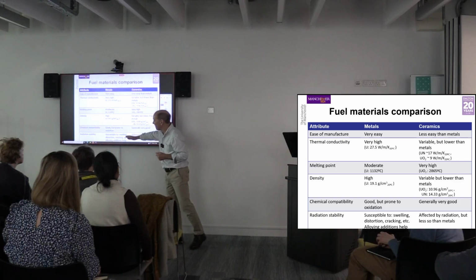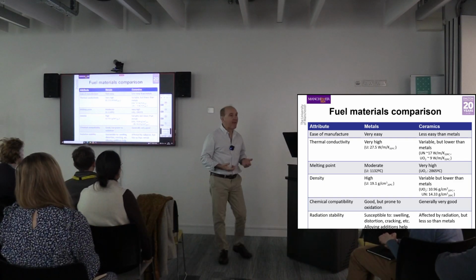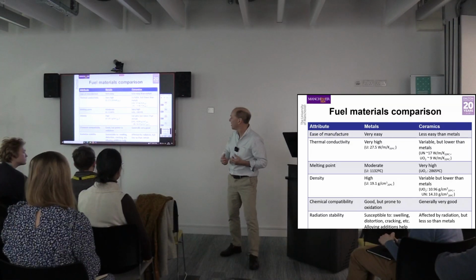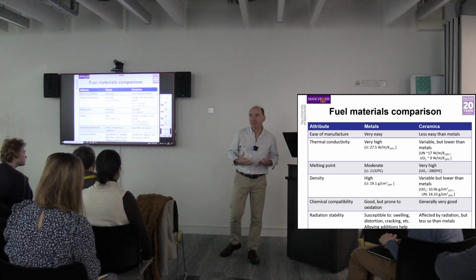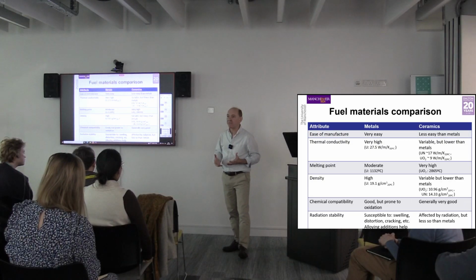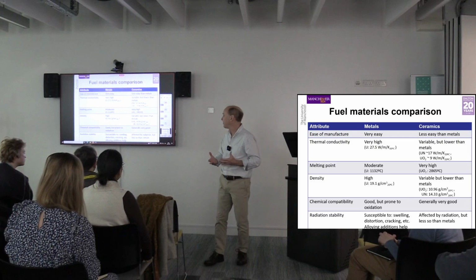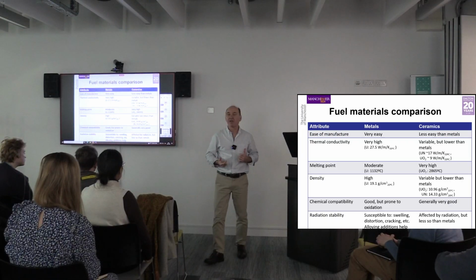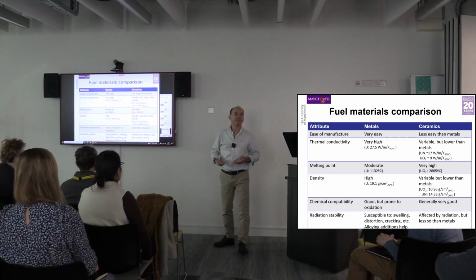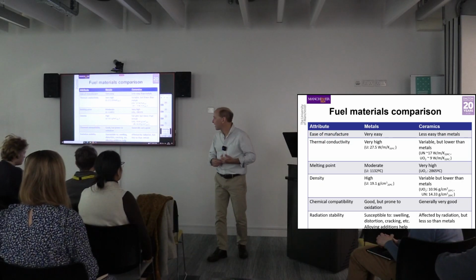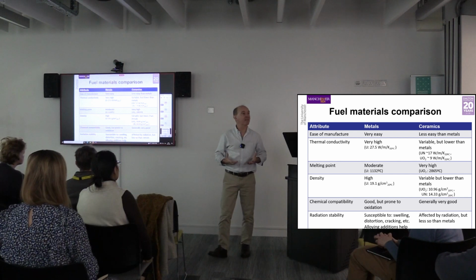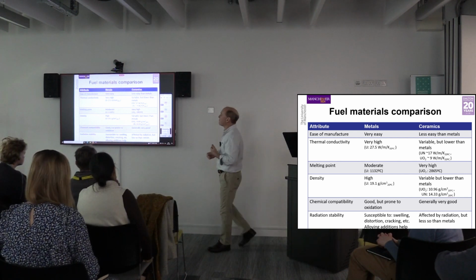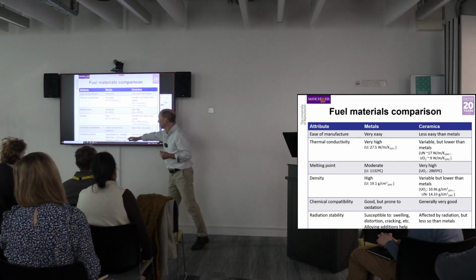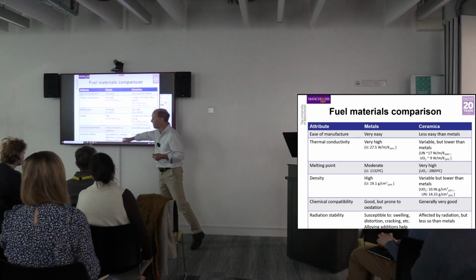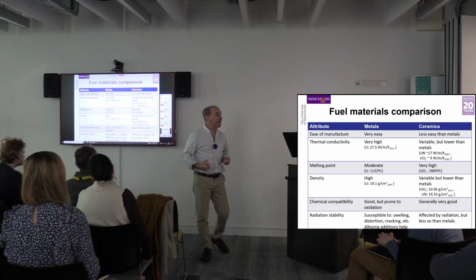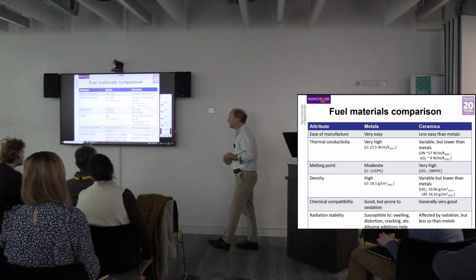And finally, radiation stability. So we're going to put these materials into the core of a reactor. What's going to happen to them? What's going to happen to their structures? Well, quite a lot, actually. Everything is affected by radiation. Absolutely everything. Nothing is immune, perfectly immune to irradiation, with the possible exception of some of the noble gases. So helium, for example, is almost unaffected by radiation, but pretty much everything else, and certainly everything with a solid structure, is very badly affected by radiation. Metals particularly so. They swell, they distort, they crack. We can add alloying additions and they help, but they don't eliminate the problem of radiation damage.